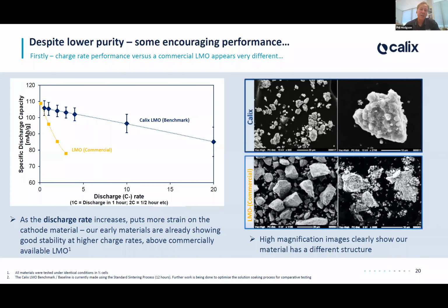Over on the right, we've taken some photos, obviously at quite high magnification, of those different materials. This is the commercial grade material. It looks like those hard crystals, fractured up a little bit. And here you can see some remnants or evidence of that high porosity morphology that goes into our crystal manufacture process. Very different process. As an indicator of the differences in performance, this could be a first step to say clearly there's a different morphology or structure of the crystal. And that is certainly a part of what we thought we would see when we started this journey. And these results, again, after numerous tests with those error bars, have borne that out.